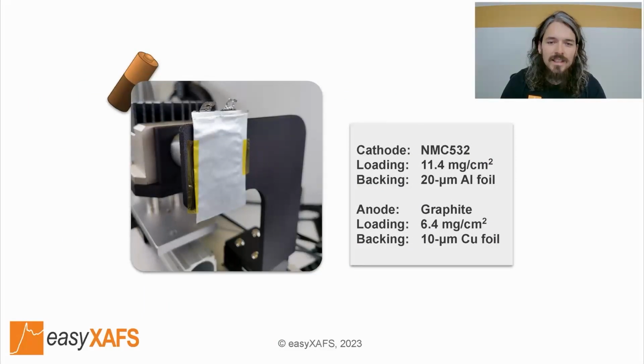Now let's take a look at a concrete example and see how the unique advantages of XAS can be applied. So here we have a fully assembled lithium-ion pouch cell. It has a nickel manganese cobalt oxide cathode, NMC532, on a 20 micron aluminum foil backing. It has a graphite anode on a 10 micron copper foil backing.